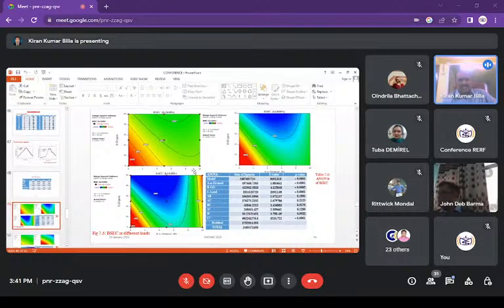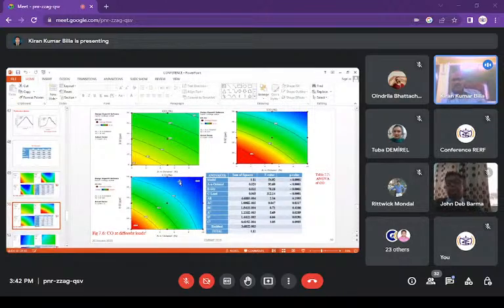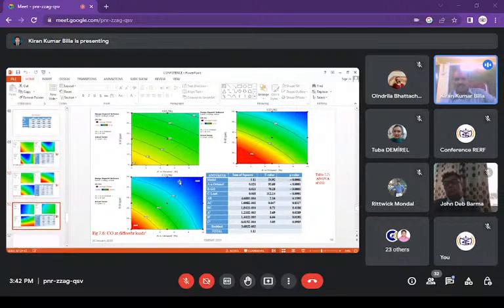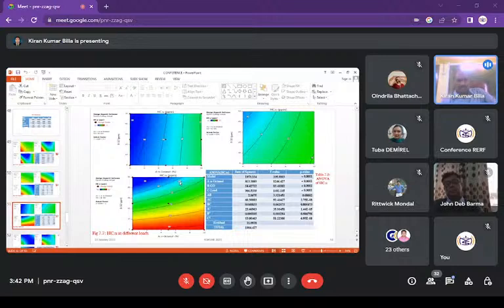For the BSFC, you can see a higher number at lower portions of N-octanol and graphene oxide. So moderate portions of N-octanol and higher portions of graphene oxide are favorable. You can see this using these blue areas. Next, coming to CO, bluish areas are favorable, as I said. So higher portions of N-octanol and higher portions of graphene oxide are favorable in this response. Coming to unburnt hydrocarbons also, higher portions of graphene oxide and lower portions of N-octanol are favored here.